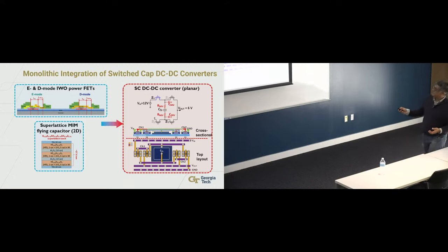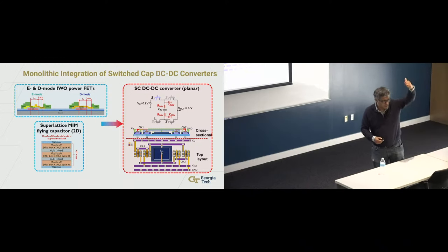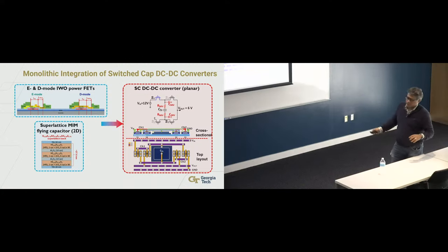So we have been having some success with these construct of a flying capacitor built monolithically using these kind of super lattice type of constructs with hafnium, zirconium oxide, alumina. Hafnium, zirconium oxide gives you that dielectric constant boost. Alumina basically is introduced only to suppress the leakage, because it has to be high density but extremely low leakage. You don't want that charge to trickle out. And then for the transistors, we are using this depletion mode and the enhancement mode devices, all monolithically integrated on chip.